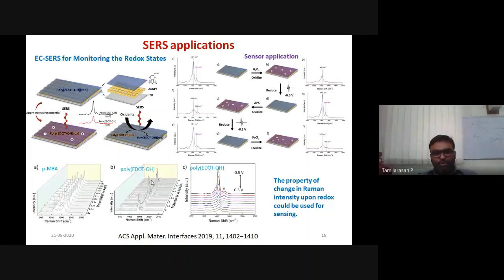This may be because of Fermi level tuning in the substrate, because there is a possibility that if you tune the Fermi level, then obviously you will tune the Raman intensity. So to confirm that it is not because of Fermi level tuning but because of oxidation and reduction, they also took MBA, mercaptobenzoic acid, and scanned it from 0 to 0.5, where there will be no oxidation and reduction for this molecule, and they found there is no change in peak intensity. That means the wavy nature you are seeing here is not because of Fermi level tuning, it's because of oxidation and reduction.